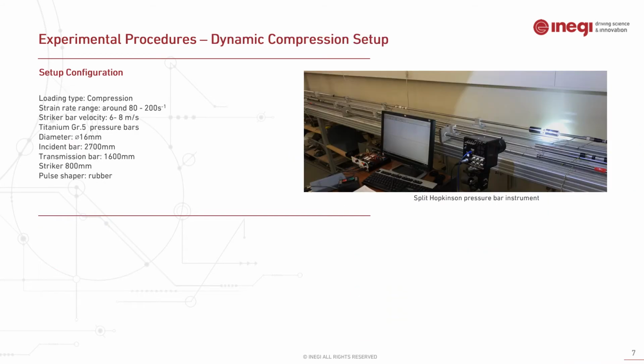The dynamic experiments were carried out using a split-Hopkinson pressure bar. We particularly designed this instrument to test composite specimens. So we chose titanium pressure bars with a diameter of 16 in order to have the right impedance mismatch between the carbon epoxy composites and the pressure bars.